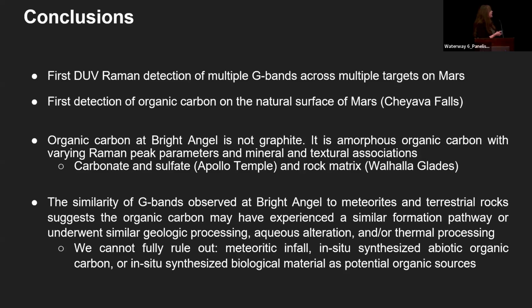So in conclusion, Bright Angel is very unique, and this is the first outcrop and area where SHERLOC analyzed that we've picked up numerous G-band signals across various targets. And it's also the first detection that we've had of organic carbon on the surface from that surface rock target called Cheyava Falls. So it doesn't appear to be consistent with graphite, but there's not much else we can say about the source or the alteration of it using just the Raman signal alone.